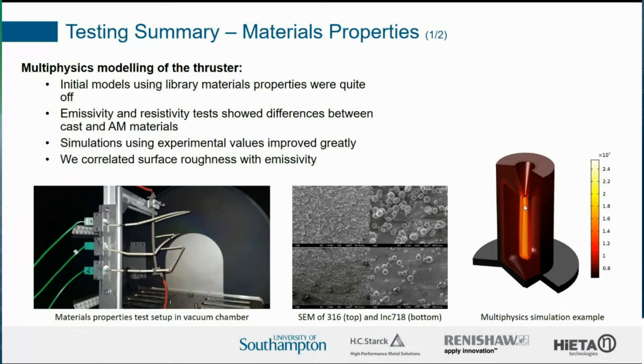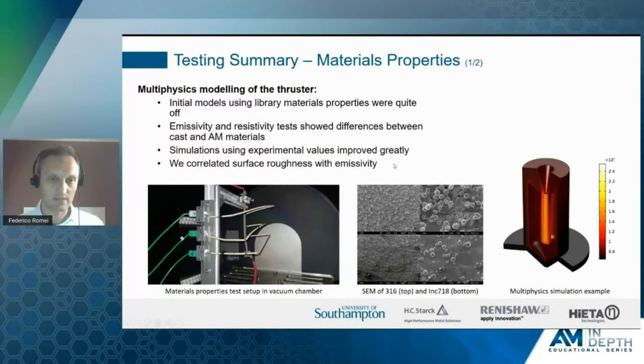And secondly, this is a resistive element. So, for instance, you have an electrical potential applied to terminals, and then you have a flow of current by Joule heating or resistive heating, as you wish. The structure heats up. So you need to know, again, the electrical resistivity very well. So that's what we've done. We have performed some tailored tests for AM materials to measure these two properties of the metals. And also we correlated, in particular for emissivity, that with the surface roughness.